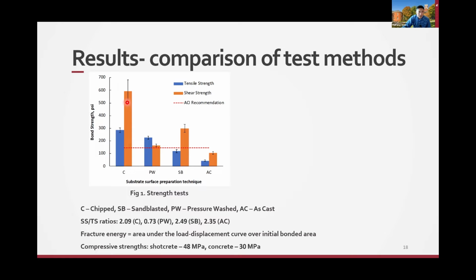You can see the chipped surface preparation gives you the highest shear bond, and interestingly, it is followed by sandblasting, which gives you a higher shear bond than the pressure washing, which is a little bit opposite compared to the tensile. Tensile for pressure washing gives you higher tensile strength. So in any case, the as-cast gives you the lowest strength, either tensile or shear.